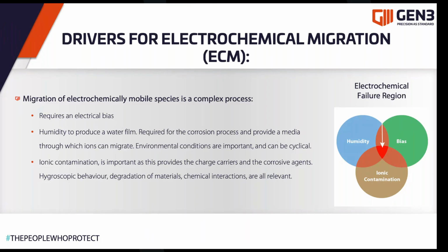Interested in the circumstances under which that can occur. As you can see from the Venn diagram on the right, there's 3 factors that are key to this. One is the electrical bias that can drive the chemical reactions, humidity, because we need a conductive layer, which in this case obviously would be water, and then we need to increase the ionic conductivity, and that is probably coming from contamination or adventitious things that have fallen onto the board. So the humidity is important because that provides the media through which ions can migrate, and the ionic contamination produces an excess of ions above that from pure water, which can help to lead to corrosion.